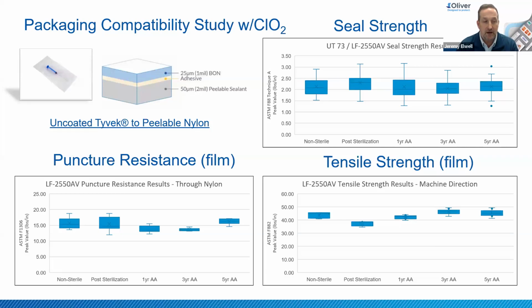And first, this is an uncoated Tyvek to peelable nylon pouch. And that structure, that diagram in the upper left-hand corner, is a detailed breakdown of the layers of the film. The outside being biaxially oriented nylon. This is an adhesive lamination, shown by the adhesive in the structure. And then on the inside, in the interaction with the Tyvek, is a peelable sealant. And these results show seal strength, puncture resistance of the film, tensile strength of the film, starting with non-sterile, post-chlorine dioxide sterilization, and then over accelerated aging time points of 1, 3, and 5 year. And this box and whisker plot of all of these shows not much effect over time or by the chlorine dioxide sterilization. So with this combination, we're very comfortable with recommending it for this application.